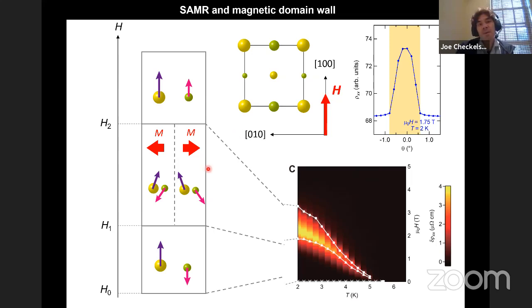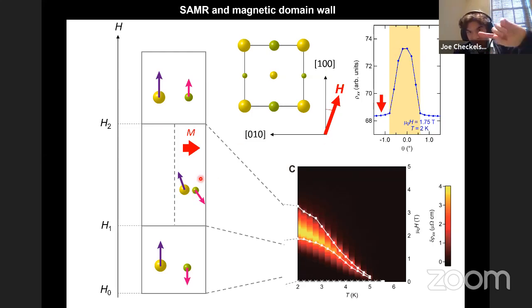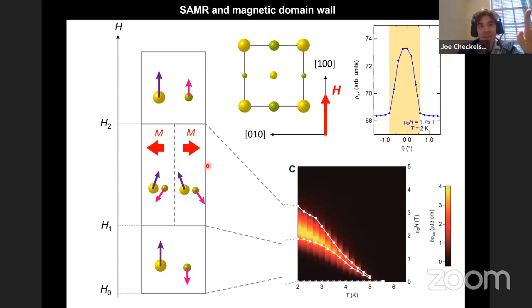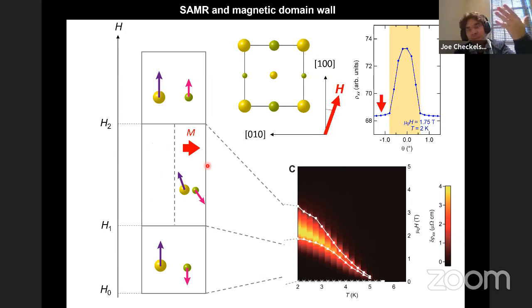So the way that we convince ourselves is that while it's true that there should be some contribution from the domains, when you think about how little you change the magnetic field in the perpendicular direction, from 0 degree angle tilt to like 0.5 degree angle tilt, you would only expect a really tiny change of the magnetic orientation. And then by studying systematically how much the magnetoresistance changes as we change the in-plane magnetic field, we can kind of rule that out.